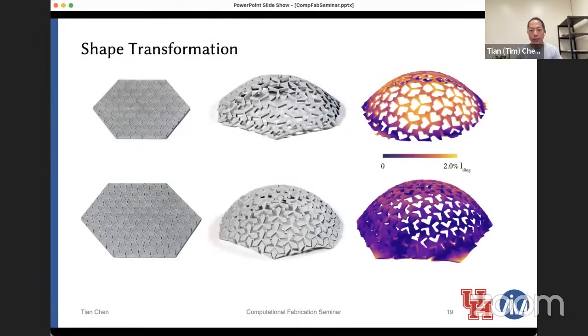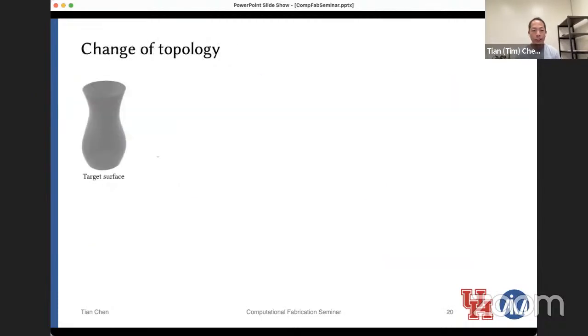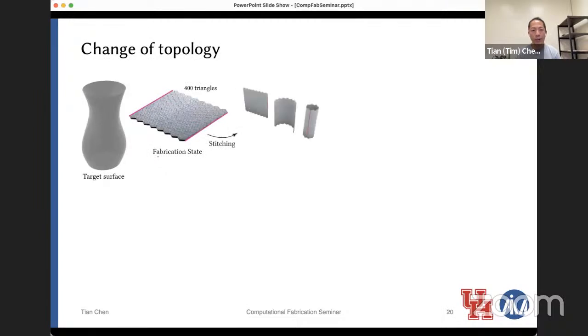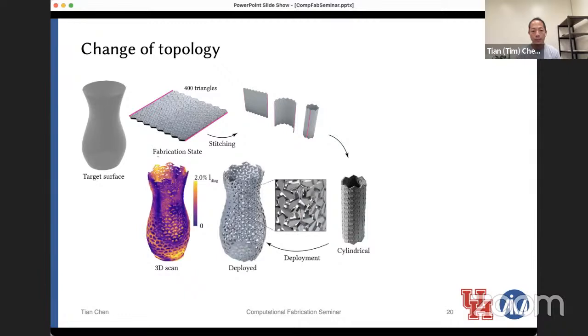And of course, we can use photogrammetry to construct the 3D geometry, or we can use other techniques like CT scanning, for example, to get a more accurate view of the geometry. Either way, it gives us the structure that we need. And we can, of course, change the topology of the system. We can have a target surface that has a cylindrical topology, and we still fabricate this flat, and then we glue the seam together prior to deployment, because we know the triangles are going to rotate in a compatible manner. So we have a cylindrical system first, and then we deploy this into the vase shape that we wanted.